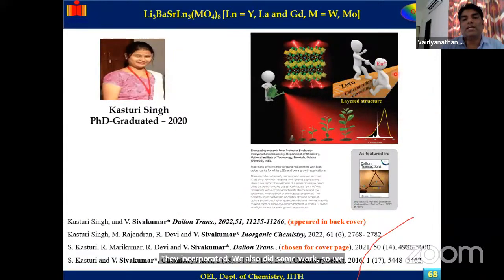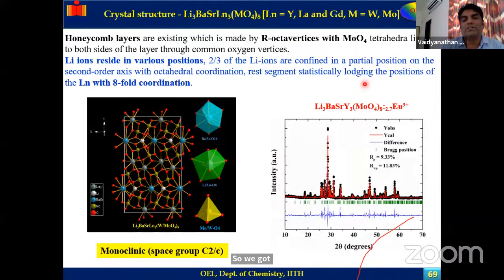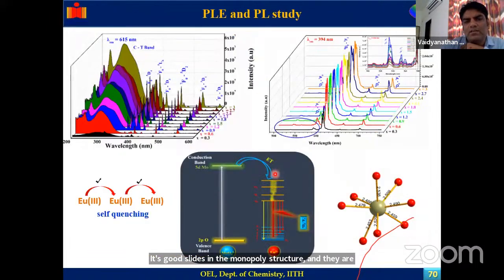So we took Li3BaSrLn3(MoO4)8. We got it published in Dalton Transactions, and this one in Inorganic Chemistry, which crystallized in the monoclinic structure, having MoO4 tetrahedra. The space group is C2/c. And you have a charge transfer spectrum and the europium 3 plus line. And you get an emission only, pure red emission.